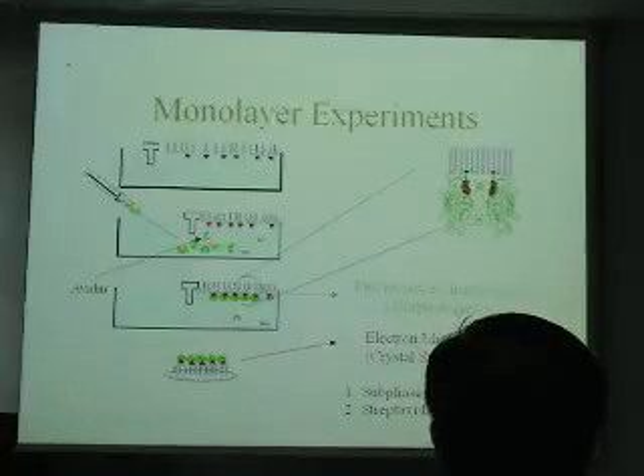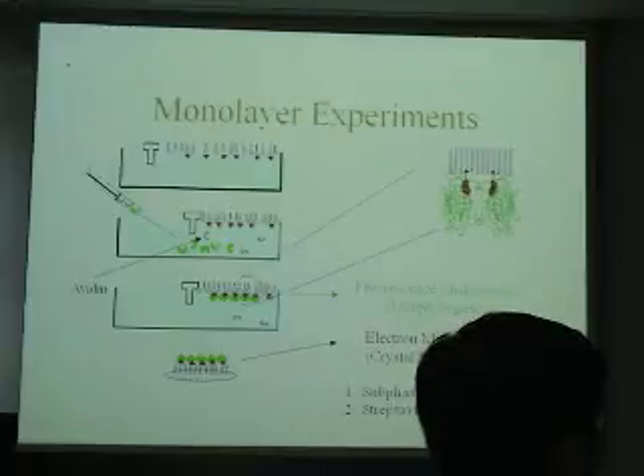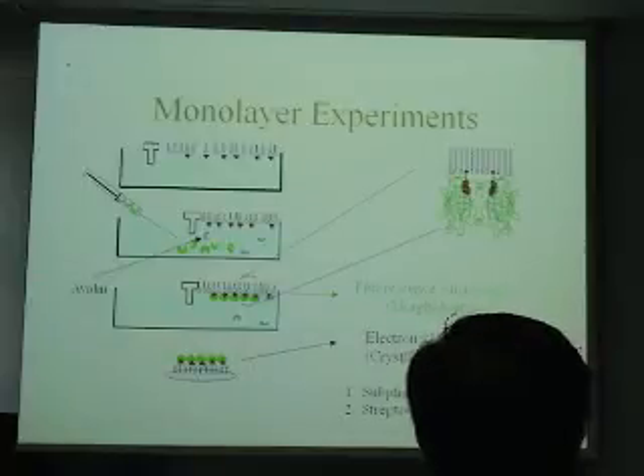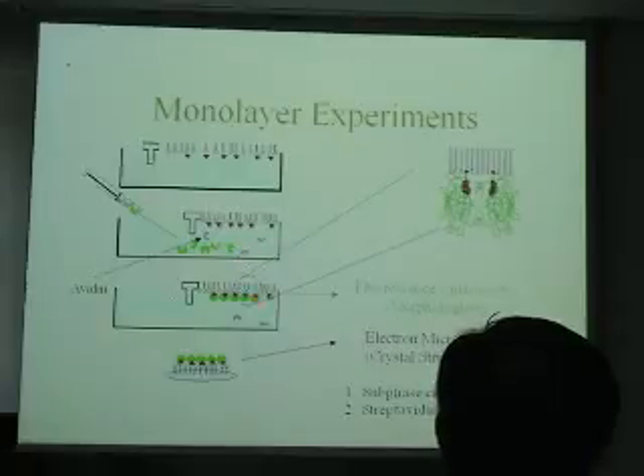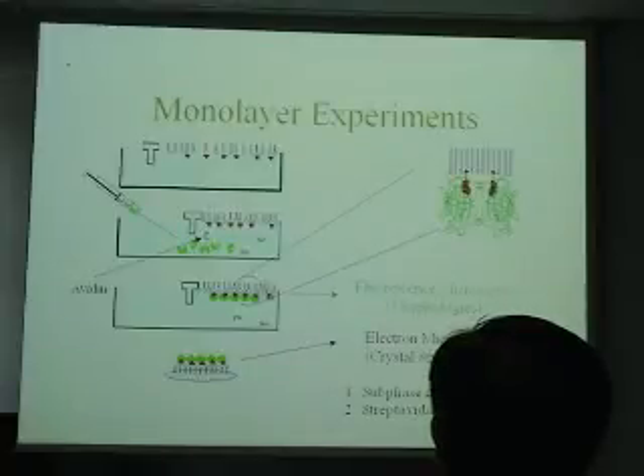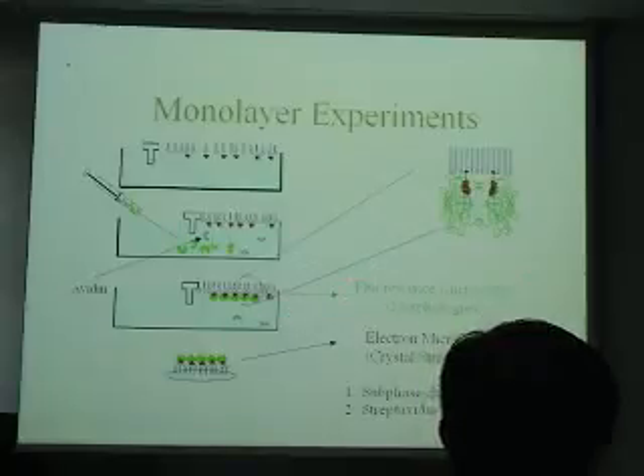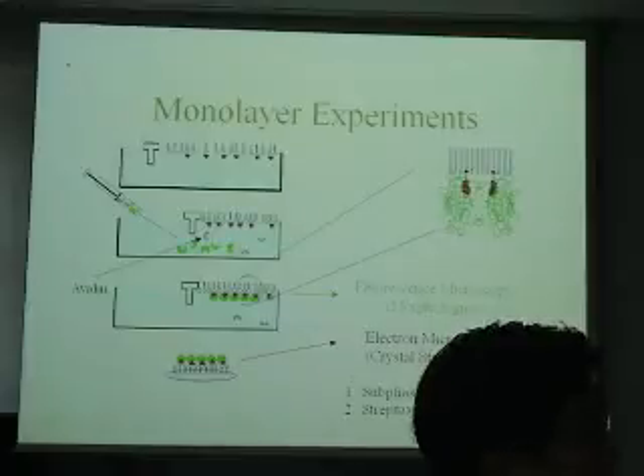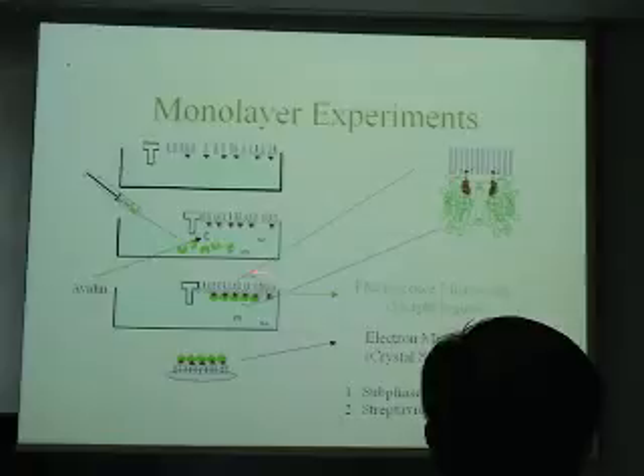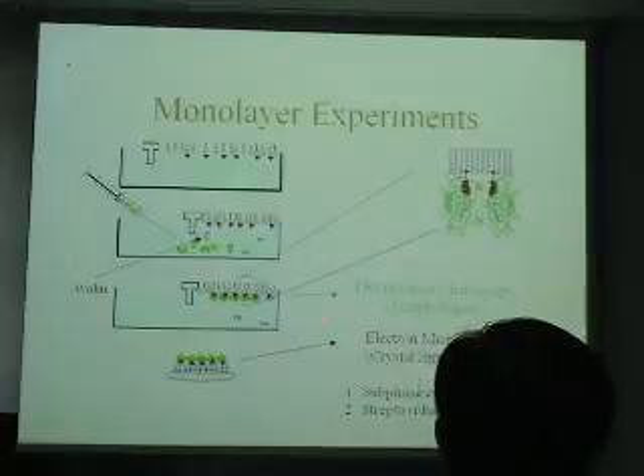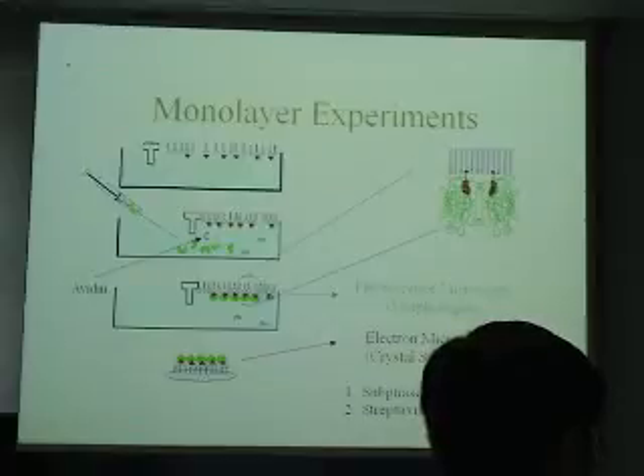I'll note that we also put in kind of a filler protein. These gray molecules are avidin. Avidin is a molecular analog of streptavidin, but it has a sugar coating on the surface. It's glycosylated, it has sugar groups on the surface, so it does not crystallize. So you can think of the streptavidin as the crystal, the avidin as the liquid or the solvent in 2 dimensions. We then look at these crystals with fluorescent microscopy to see the structure, the morphologies. And then we transfer these crystals to electron microscope grids and look at their crystal structure. We focused on changing the subphase to manipulate the interactions to change the crystallization behavior, and then we did mutagenesis to be more specific with our interactions.